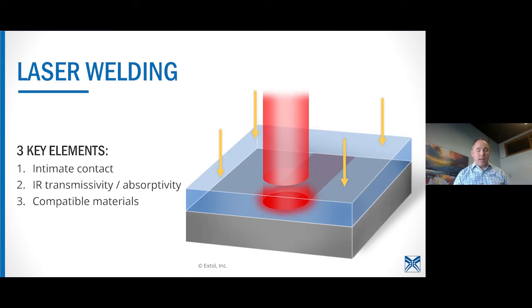IR transmissivity and absorptivity we'll talk about a little bit more in the myth section here. But that's crucial as well to make sure that you have that proper heat conduction up to that transmissive layer. And then compatible materials is the same as any welding technology. We do a lot of different welding here at Extol, and you have to make sure that you have the proper chemistry between those two parts, so you have similar melt temperatures, and that those materials can in fact weld to one another.